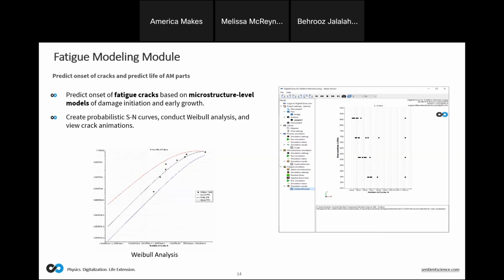That's exactly what happens also here in our simulation. As you can see on the SN curve, even for a fixed load level, we are providing a range of fatigue lives, which later on can be used for any statistical analysis, for example, for Weibull statistical analysis, as it's shown here on the left-hand side. Then of course you can calculate your Weibull slope, which is a measure of how much scatter you have in your set of data, and then also you can produce L10, L50, those statistical life values based on your application. This is also something that is provided here through our DCAM. We are providing the Weibull parameters when the simulation is done. Go to the next one, please.